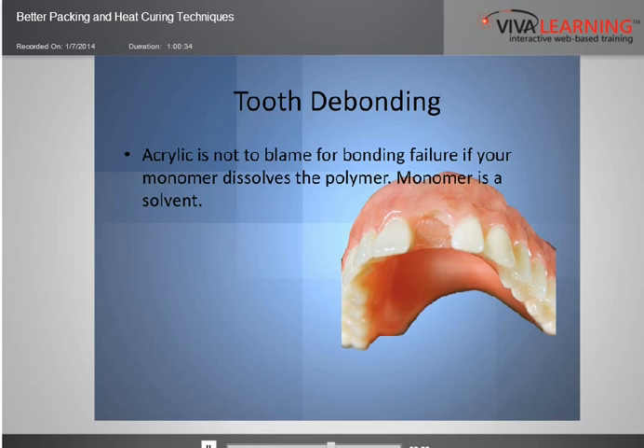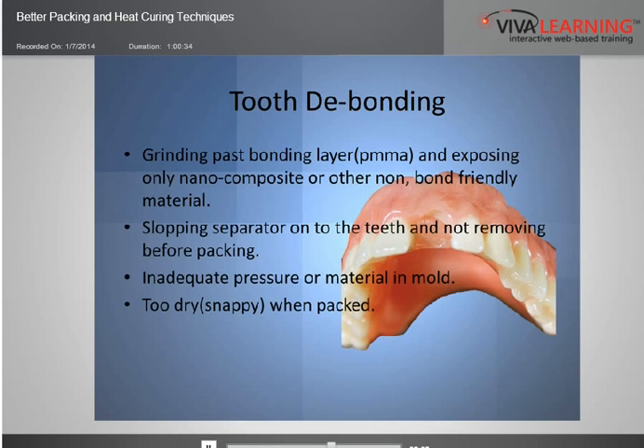Tooth debonding some more. Grinding past the bonding layer, and I don't know if people are aware of this. These really beautiful nanocomposite and hybrid composite teeth get their characteristics from a non-bond friendly material, which is basically composite resin or tightly networked acrylic. And so in the manufacturing process, they put a little bit of PMMA resin, acrylic, on the necks of the teeth. But with these cases, and you know, what cases don't you have to grind on? Even more so probably on these bar cases that we're doing. But the fact is that if you grind and grind and grind, and you grind off that PMMA layer that they have there, and expose only that nanocomposite or other non-bond friendly material, you're not going to get the bonding unless you put some sort of mechanical retention.